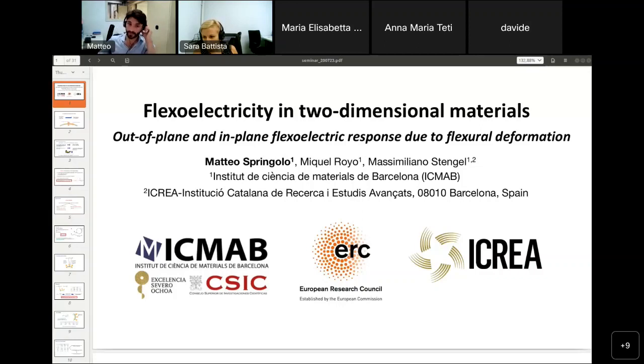This is a very good point, because, well, I can show a slide. Actually, piezoelectricity here is more important, because in a two-dimensional material there enters also the so-called local piezoelectricity. I mean, for example, usually in bulk materials, we consider just the so-called genuine flexoelectric response. That means that we are considering only one part, the macroscopic effect. When we consider a system with a reduced symmetry, there is a further contribution that comes from the local piezoelectricity. This is very important in this kind of system. Indeed, let me show a figure if I can.